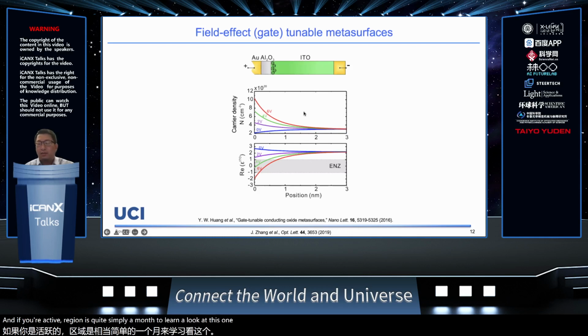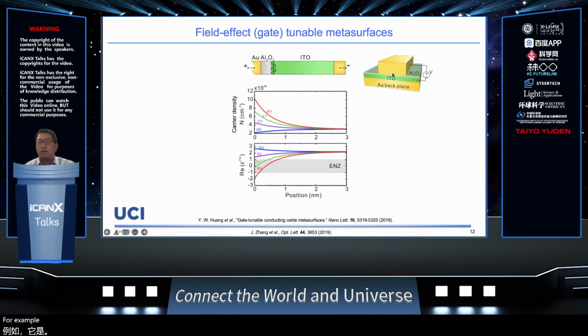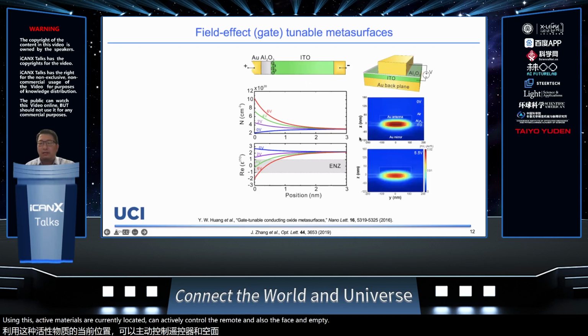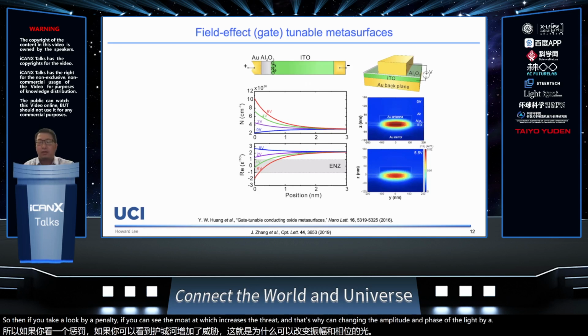That's why you need to combine it with a highly confined structure, for example this kind of metasurface structure, to make the tunability really efficient. So we integrate this active material into a metasurface resonance structure. By applying the voltage, you can actively control the mode and also the phase and amplitude. If you look, by applying voltage, the mode changes quite significantly, and that's why you can change the amplitude and phase of the light by applying electrical voltage.